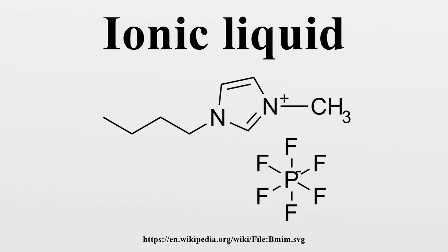ILs are attractive because of their low vapor pressure, increasing battery life by drying slower. Furthermore, ILs have an electrochemical window of up to 6 volts, supporting more energy-dense metals. Energy densities from 900–1600 watt-hours per kilogram appear possible. A metal-air battery draws oxygen through a porous ambient air electrode and produces water, hydrogen peroxide, or hydroxide anions depending on the nature of the oxygen reduction catalyst and electrolyte. These compounds store the electrons released by the oxidation of the anode.